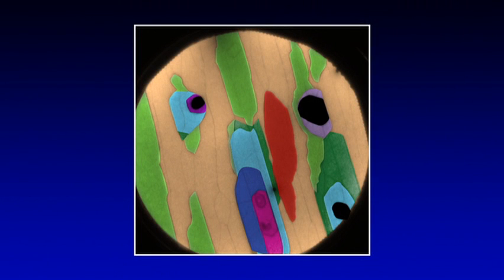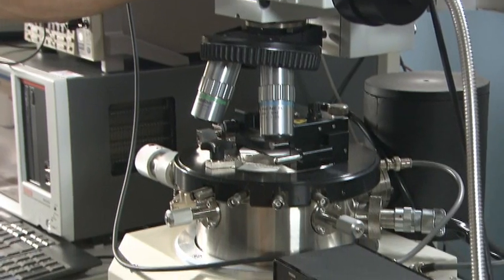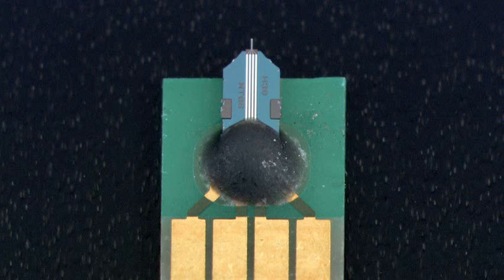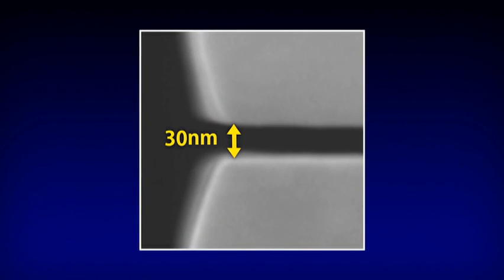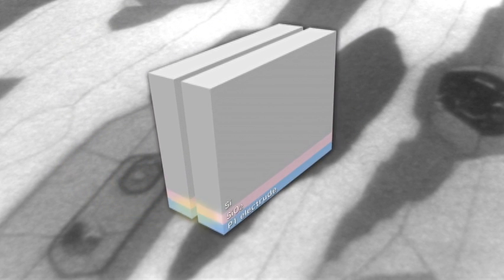We are also using an integrated nanoprobe, which is able to measure the current between two electrodes on the tip of a silicon cantilever, to reveal electrical characteristics of the samples. Through these observations, we have been able to understand the relationship between the number of graphene layers and electron conductivity.